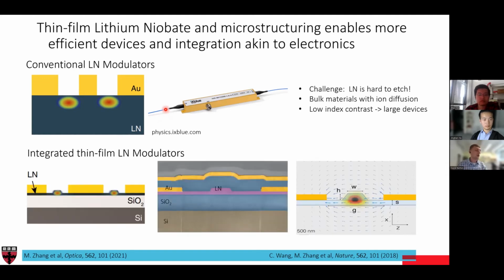But recently people have been able to commercially deploy thin film lithium niobate. That looks like the bottom left here, where we have a silicon wafer, silicon dioxide handle or a buried oxide, and we can deposit or bond thin film lithium niobate. And developments by both my group that I'm currently in, as well as many other groups around the world, have been able to engineer new ways of nanofabricating this material and making very high quality optical waveguides on a chip that allow us to make very efficient, very high speed and low energy modulating devices that can actually compete with or outcompete devices that are commercially deployed in their bulk counterpart.